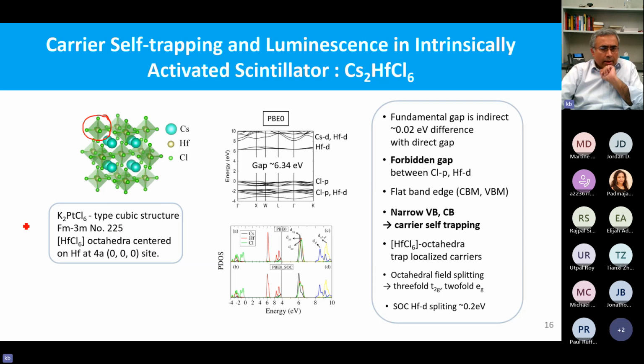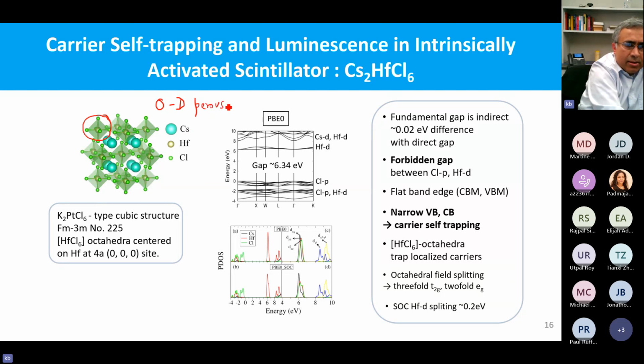These cesiums are in cubo-octahedral cavities. These cesium atoms have 12 chlorine atoms from different octahedra surrounding them. So the octahedra are linked with other octahedra not directly, but bridged by these intervening cesium atoms. That's why sometimes they are also called zero-dimensional structures or zero-dimensional perovskites. Sometimes they are mentioned like that in the literature. Why? Because the octahedra are isolated from each other. They're not connected to each other. So that's a little detail about the structure.